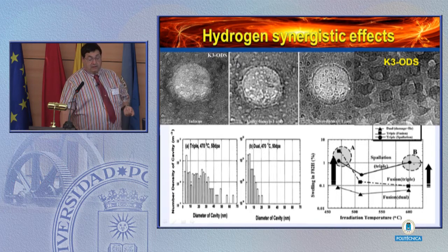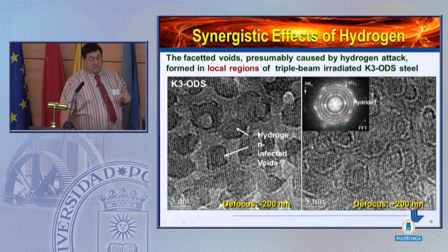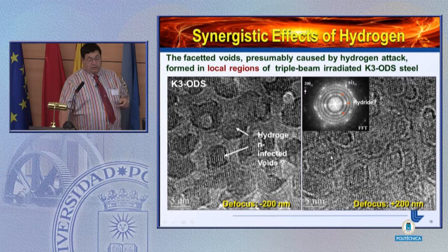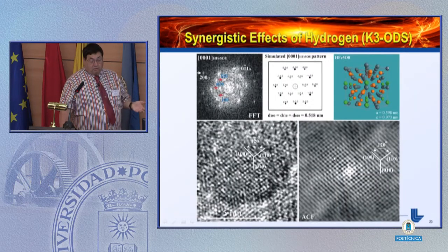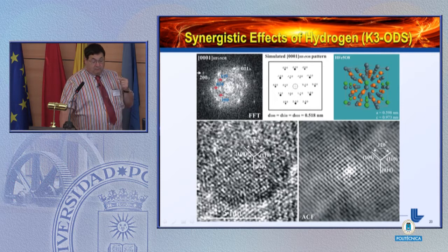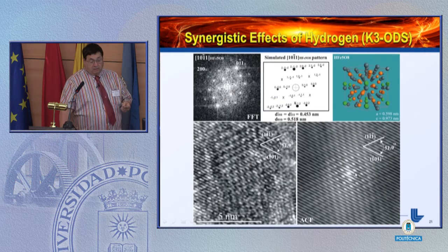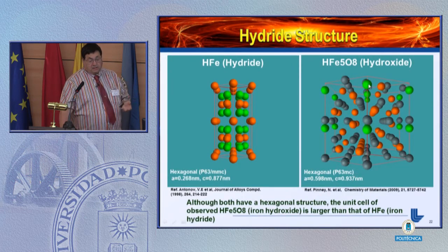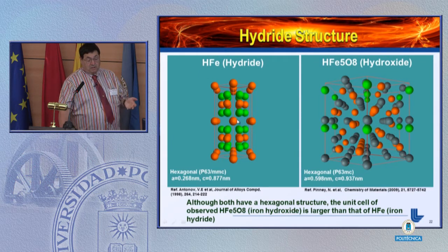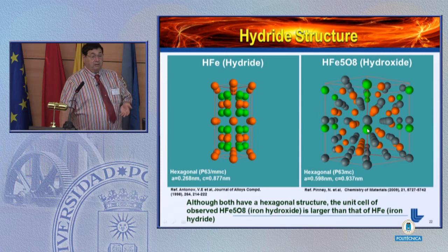This free oxygen is interacting with the hydrogen. And now you see some high resolution pictures of these infected voids, we call them. But it turns out there's no hydrogen there. But from doing diffraction analysis in the high-resolution microscope, we actually were able to identify that these were hydroxides. At first we thought, oh, maybe these are iron hydrides, but they weren't. They had similar characteristics, but it turned out that this is some form of hydroxide. This is bad news, because these hydroxides embrittle materials very quickly. So now we have an effect that we really have to worry about.